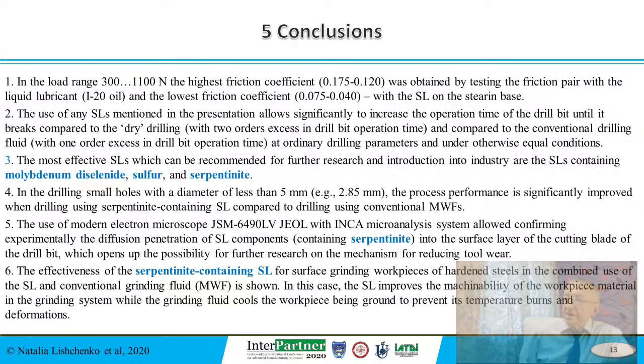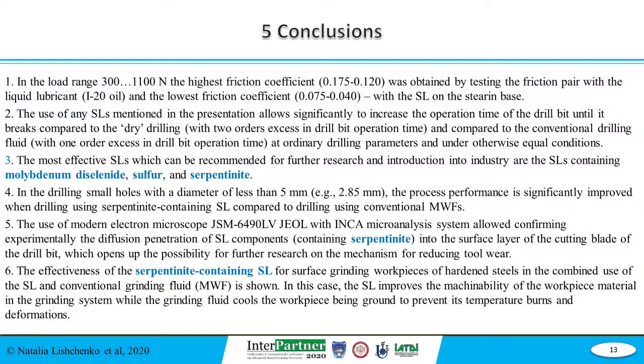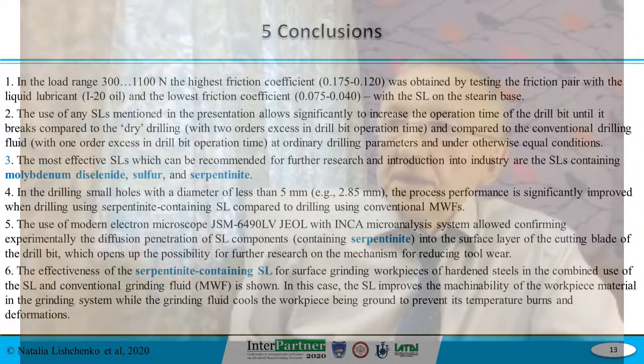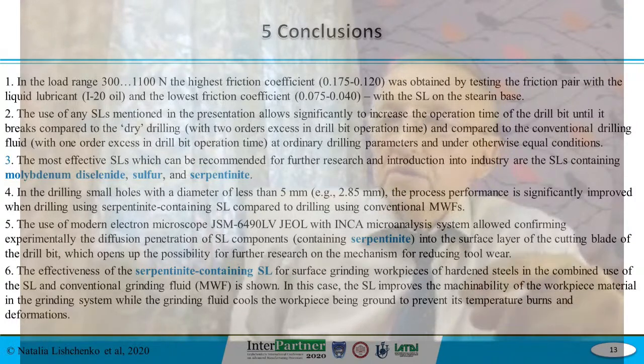At ordinary drilling parameters and under otherwise equal conditions. That said, the most effective SLs which can be recommended to the further research and introduction into industry are the SLs containing molybdenum diselenide, sulfur, and serpentinite.